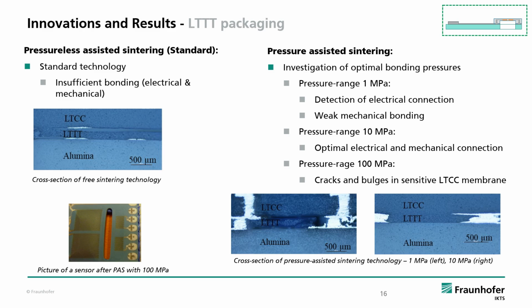In the pressure range of 1 MPa, an electrical connection is there, but as you can see in the cross-section, the mechanical joint is weak. In the pressure range of 10 MPa, we had found the optimal parameters. We have a good electrical and mechanical connection. You can see on the right.